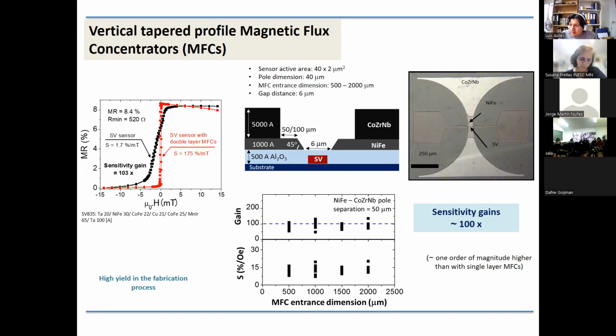And also, if you look at the TMR sensor, and I think you may know this well, the resistance is normally a specification by the supplier. So they ask us, you need a sensor with 1 kilo ohm, 2 kilo ohm, 2.2 kilo ohm. They do the same for GMR. And the resistance in a TMR sensor depends not only on the geometry, but depends dramatically on the thickness of the tunnel barrier. And here we are talking about tunnel barriers that are 1 nanometer, 1.1 nanometer MgO. And if in one wafer we have from 1.1 nanometer to 1.15 nanometer, so half an angstrom on average, this can increase the resistance by 1 order of magnitude, or decrease it by 1 order of magnitude. So this is actually a killing factor most of the time with the TMR wafers.